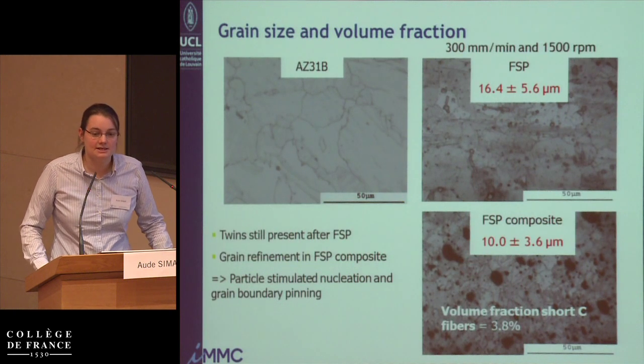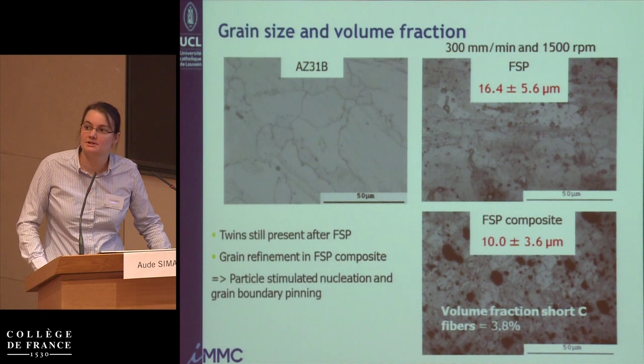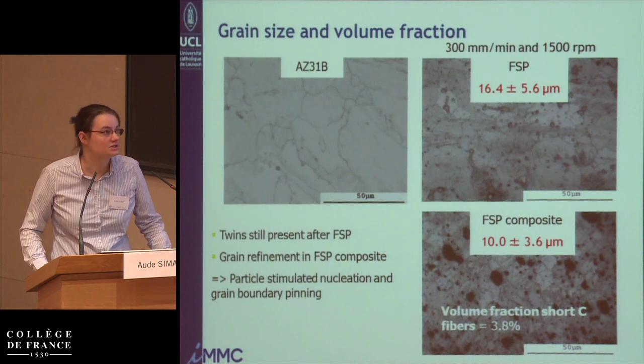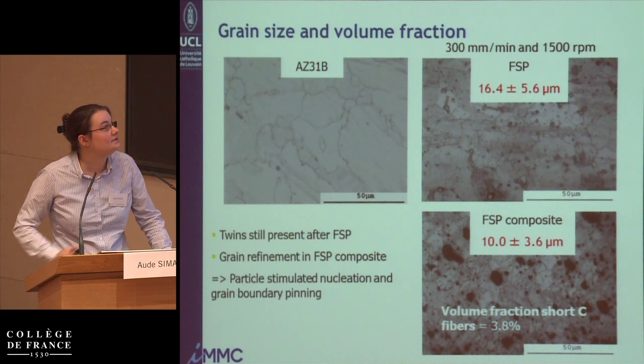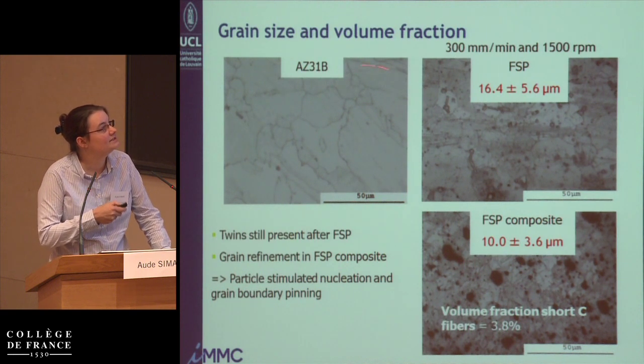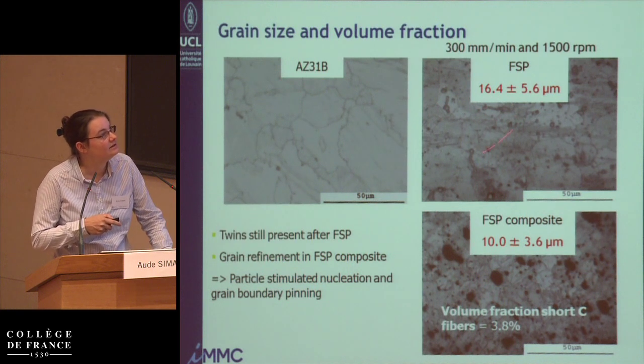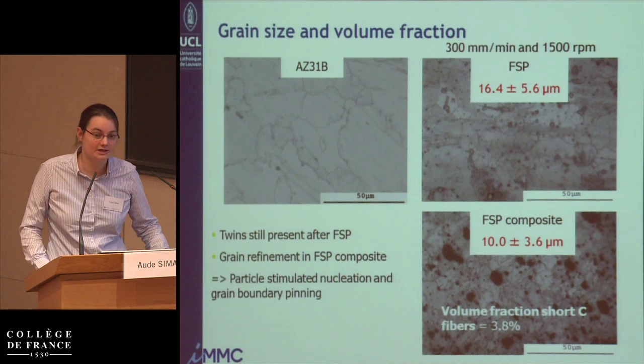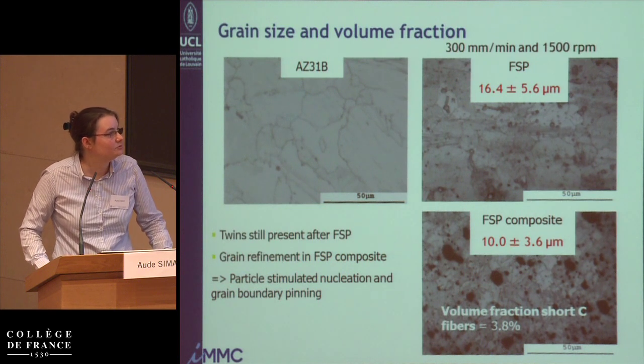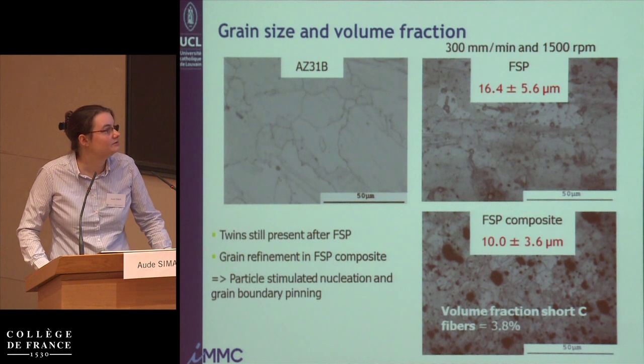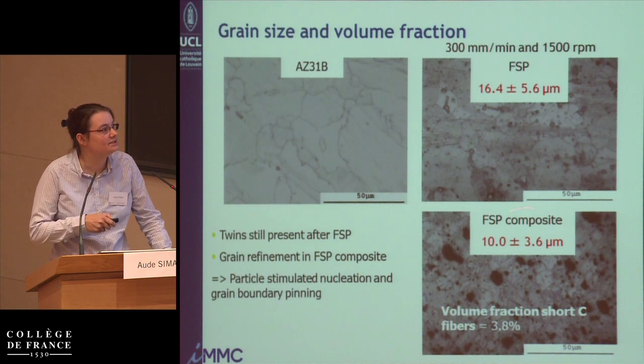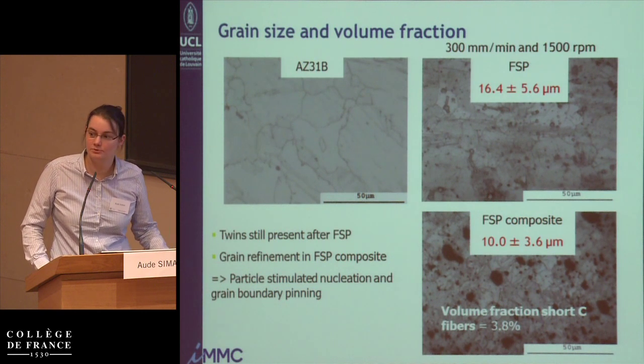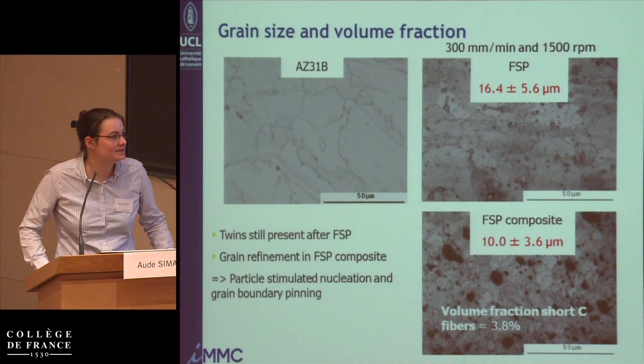Now, looking at the grain size, I've told you that the grain size definitely decreases when you do friction stir processing. And so this is the grain size in the base material. And then in the friction stir processed material, you have recrystallization. And you still have some twins that are present in the material after friction stir processing. So it's not a full recrystallization, and you have significant decrease also in size from 16.4 micron to 10 micron when you actually put the carbon fibers in the material.